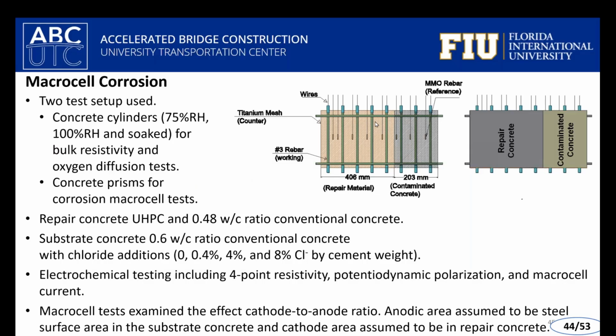Looking more in terms of retrofit and using UHPC in a mixed environment, mixed with normal strength concrete for repair applications essentially, some testing was done at FIU to look at the extent to which what we call macrocell coupling can develop. So what does that mean? There are many cases in piles and columns for bridge work where we have damage that occurred even after a retrofit.